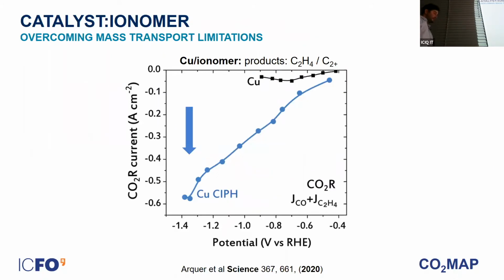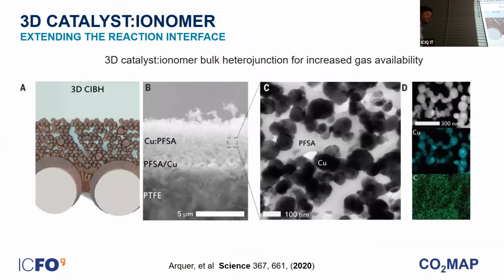When we actually implemented these electrodes into the reaction that we want to improve, we observed a dramatic increase in partial current density, in productivity. You can see here for copper without the ionomer, the partial current density saturates, and the limiting current is around hundreds of milliamps, as we've seen in the previous example. But when we add the ionomer on top, you can see a six-fold improvement in the partial current density for the CO2 reduced products, in this case CO and ethylene.